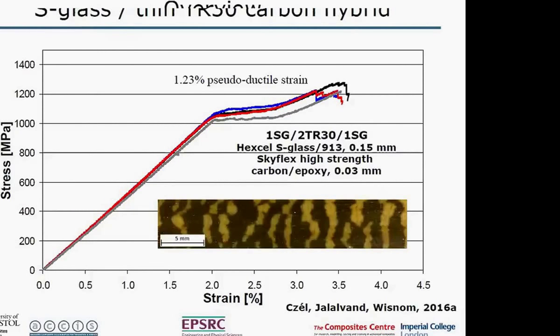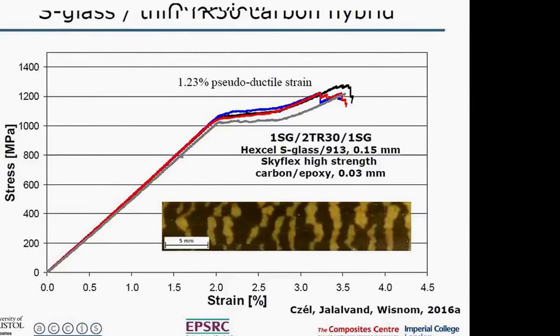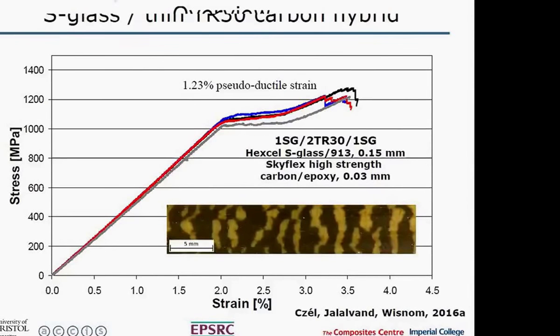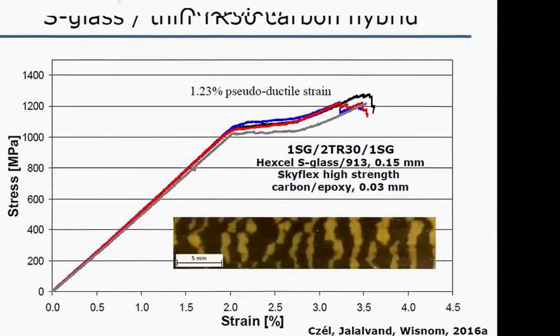So this is quite interesting because as well as generating the pseudo-ductility, it can be used as an overload sensing mechanism. And this is something we've also been doing quite a lot of work on, how we can exploit that to not only get this pseudo-ductile response, but to be able to actually have either a surface layer on the structure, which indicates overload, or you can have a discrete sensor, which can be bonded on. It can be bonded on metal structures, and that can be composite to give an indication when a certain strain has been exceeded. And it can also be used on looking at fatigue response as well. That's a whole other story which I'm not going to talk about today.